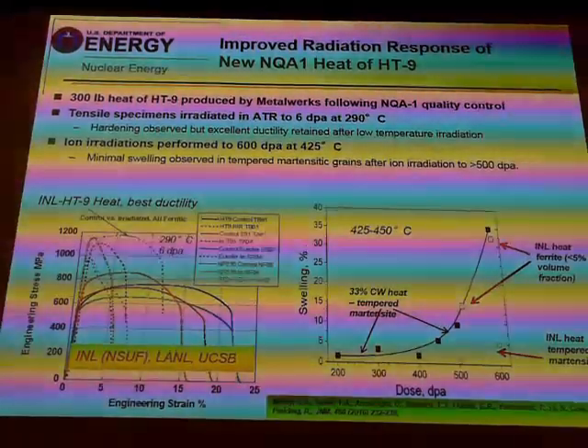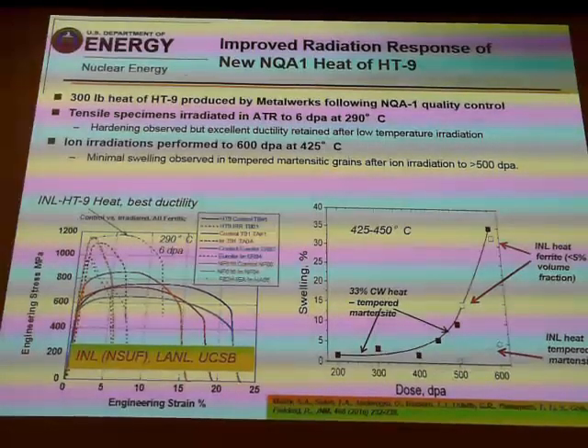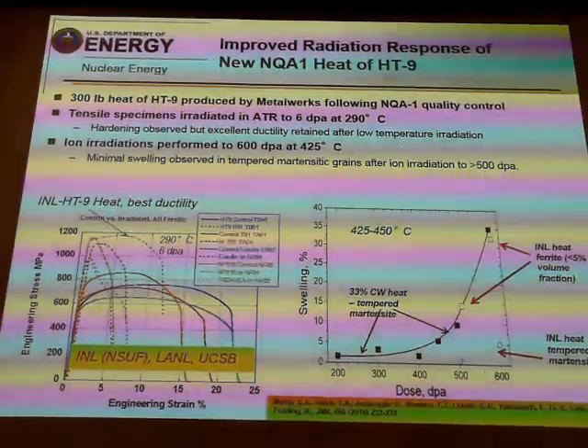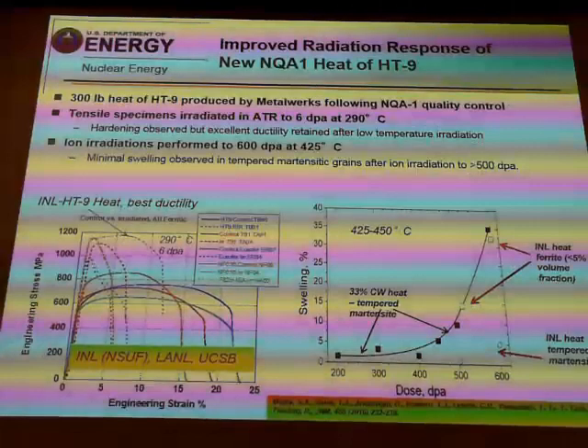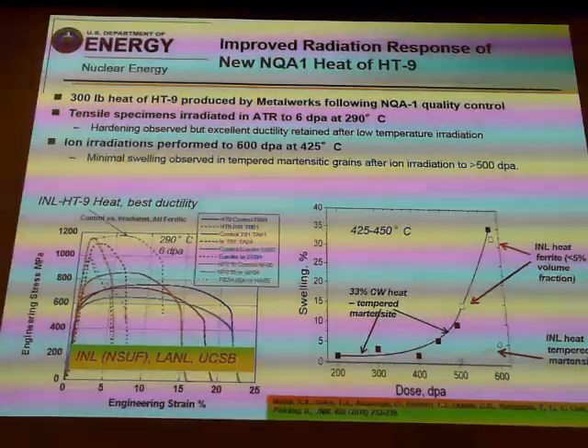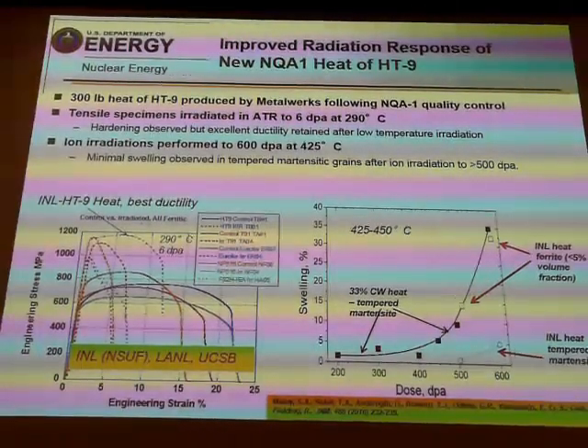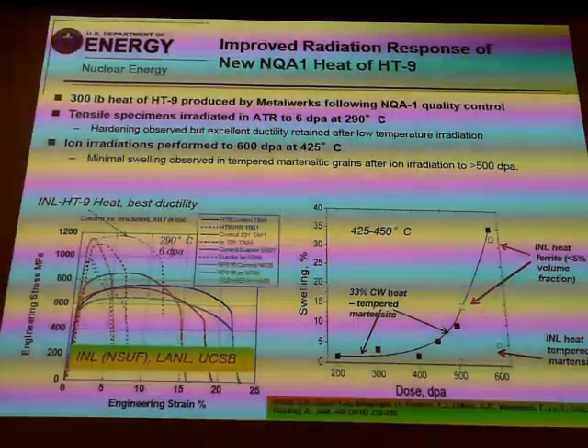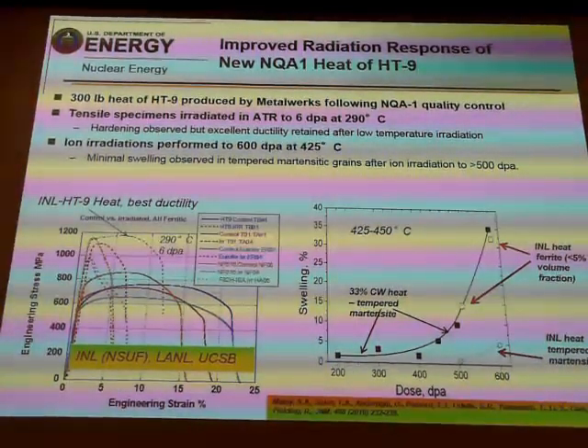Let me also talk to you about some improved materials that we're working on. We had a new heat of HT9 made following just typical NQA-1 standards, and we did tensile testing on those materials after irradiation. It turned out that this HT9 material showed almost over 5% uniform elongation at irradiation at 290 degrees C up to 6 dpa. So it retained ductility in a regime where you don't see much retention of ductility.